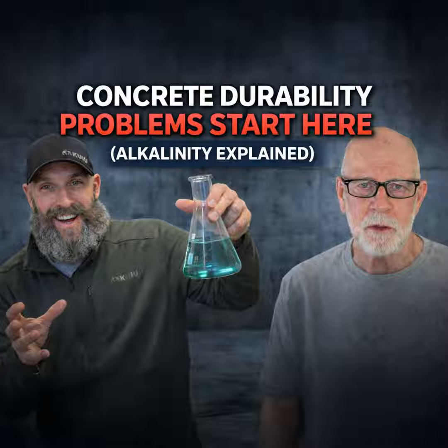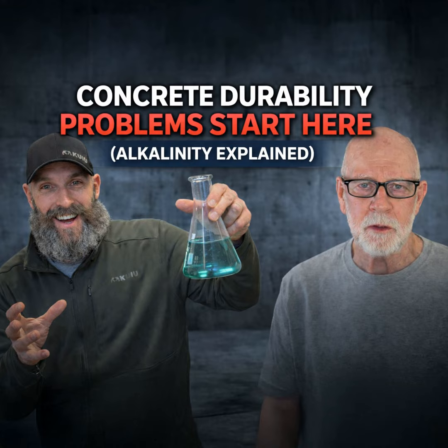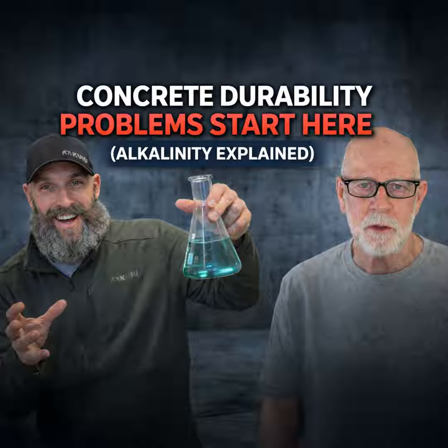And if you look at where they have sodium hydroxide in bulk, where they ship it at 40%, that's typical, 40% concentration in water, they have to keep it heated at 70 degrees, because here's another strange property. Sodium hydroxide, as it gets concentrated, and here's the problem. The state-of-the-art study on concrete in NIST in 1999 said that sodium hydroxide is an antifreeze. And they showed a truncated graphic. It showed up to 20%. It would drop the freezing point of water to negative 14 degrees Fahrenheit. Well, that's true. However, it doesn't stay at that.